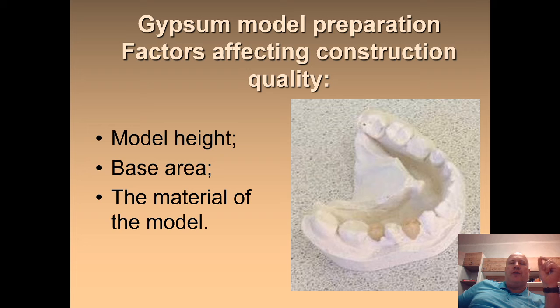The second factor on which the height of the model has an effect is the deformation of the thermoplastic. As the height increases, the plastic should deform to a greater degree, which leads to thinning and weakening of the material of the final accessory. Base area, this is the second part. The larger the base area, the greater the number of suction openings covered, and therefore the suction suitable for plastic deformation is greatly reduced. The key to the solution of this problem is to make the base as small as possible in order to get the most out of the vacuum molder, or to make a fenestrated model. This is not a problem for vacuum molders using pressure, but those are much more expensive.